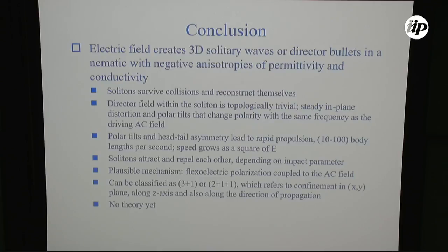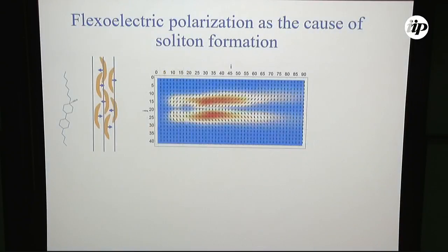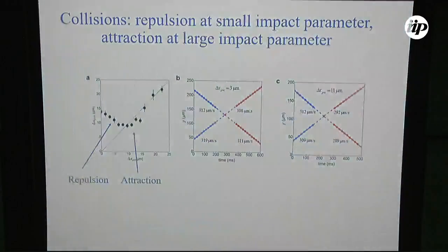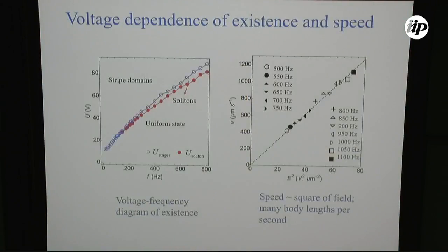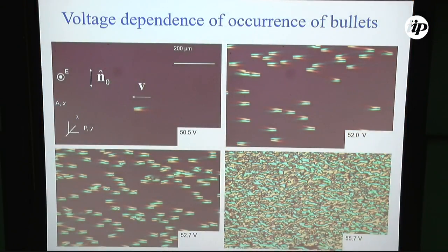We are approaching electrohydrodynamic instability that occurs everywhere. So now the perturbations are not localized. They are just essentially everywhere. It's the well-known pattern of stripe domains. That typically this pattern occurs immediately from the uniform state in many other liquid crystals.